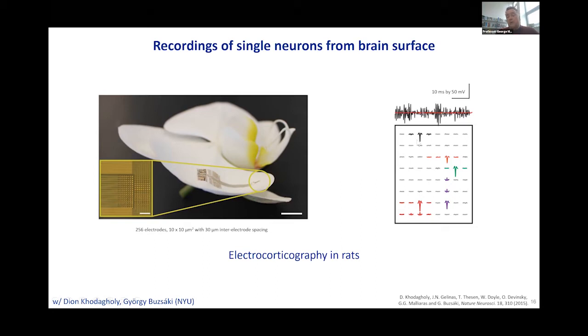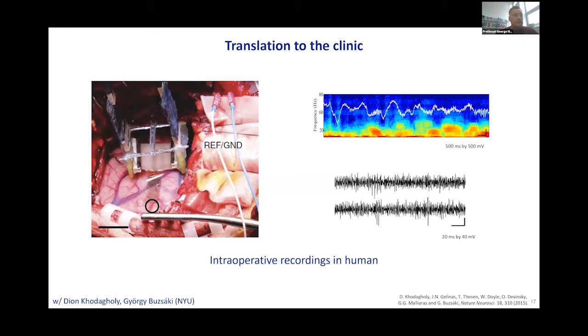So when these were placed on the cortex of a rat, we were able to record these blips here that correspond to the firing of single neurons. And for the first time, we were able to record single neuronal signatures without penetrating the brain. Now, this has overwhelming advantages because you can now sit at the surface of the brain without disturbing the neighborhood of neurons and still be able to record them. And as such, it was translated to the clinic. So now this is used in over 20 hospitals in the US to record from the human brain at very high resolution. You get global activities that are called local field potentials that you would get with traditionally larger electrodes. But you also get these little spikes here that correspond to the chatter of single neurons. So exceptionally high spatial resolution recordings.